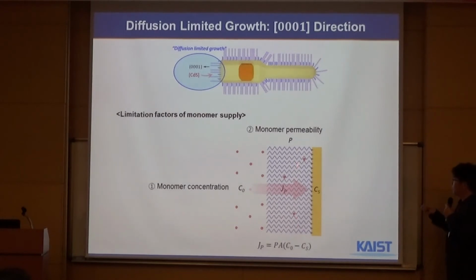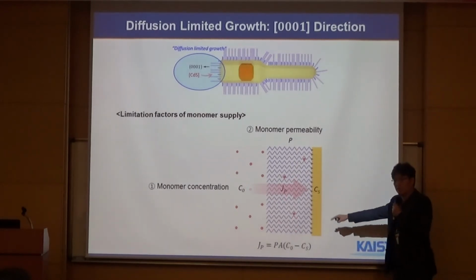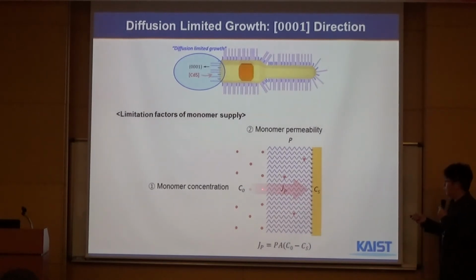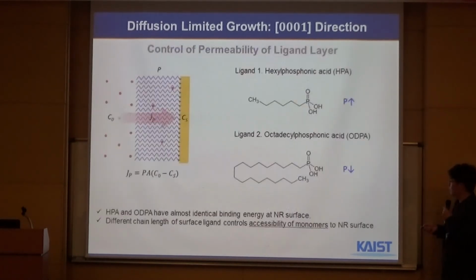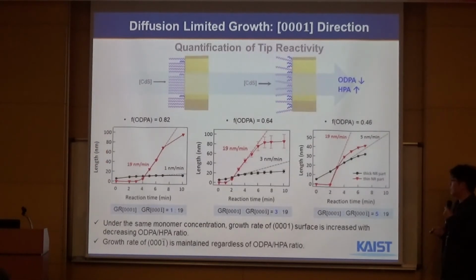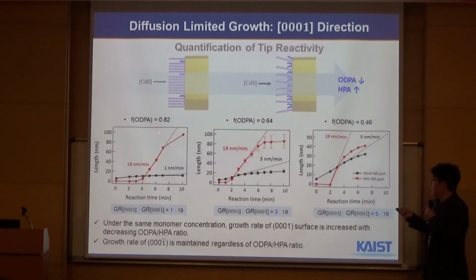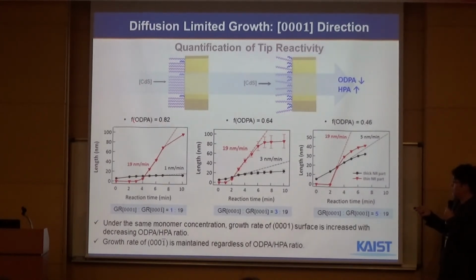And from the studies, I'm going to probably skip some details, but we were able to identify that the ligands on the surface play a very important role in whether the monomer is diffusing through this monolayer better or not. By changing the monomer composition or the ligand composition, we were able to see the control of the growth. And by using hexylphosphonic acid or octadecylphosphonic acid and their interplay between the two ligands, we were able to see that a different fraction of octadecylphosphonic acid will result in different growth rate, especially in thick nanorod parts.